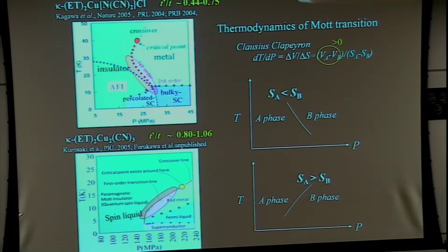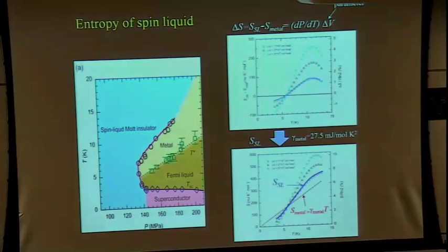And let me emphasize that in spin liquid materials, the spin entropy is still alive at low temperature. However, please take a look at the low temperature behaviors. This slope gradually changes in the tangential at low temperatures. So we proceeded to the detailed experiments to determine the precise phase boundaries.